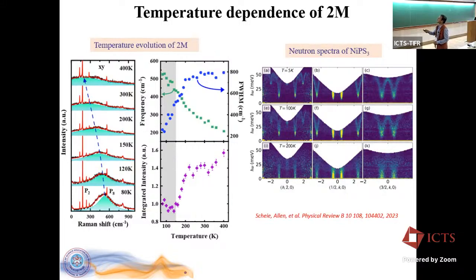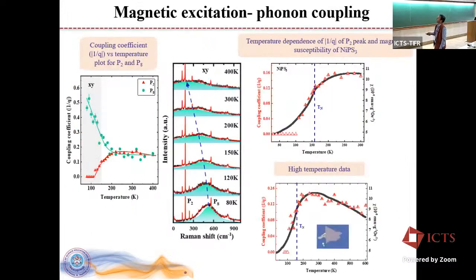The corresponding line width is captured here; this is the frequency and this is the line width, and this is the intensity. The intensity also increases. People earlier reported only in this range. Now he's found that the integrated intensity, basically the area under the curve, also keeps on increasing. This is a neutron study which said the 2 magnon was present even at higher temperature above Néel temperature. And from the asymmetry parameter, he figured out that there is a coupling of that phonon with this magnon.